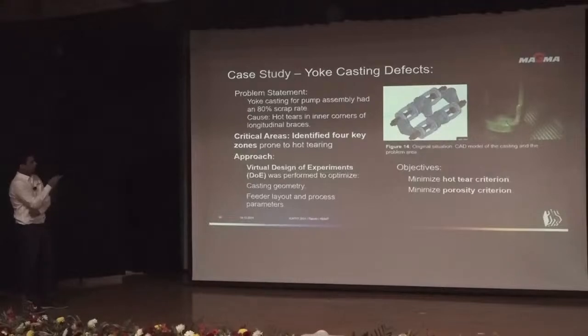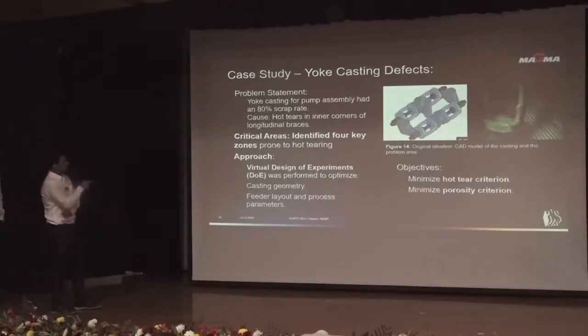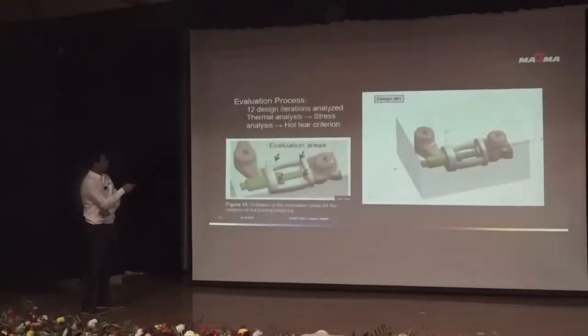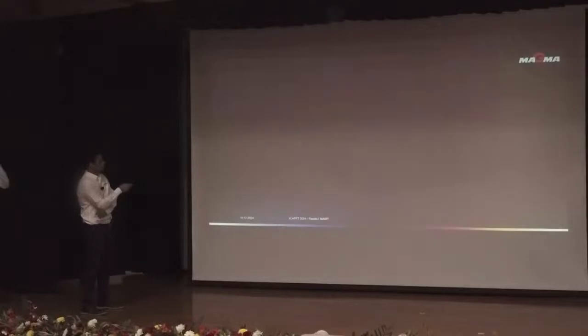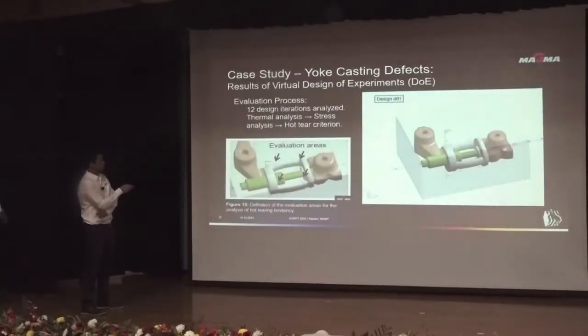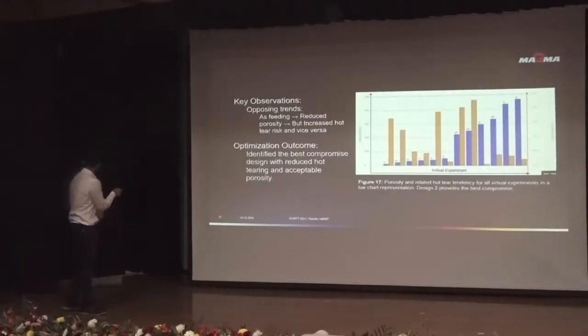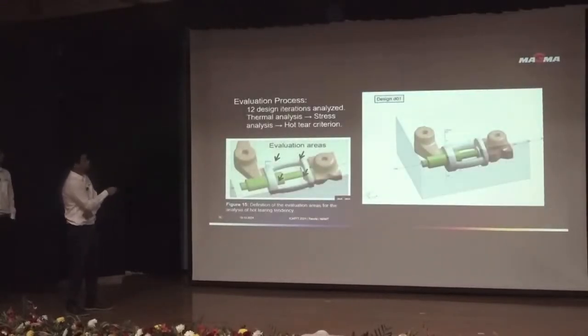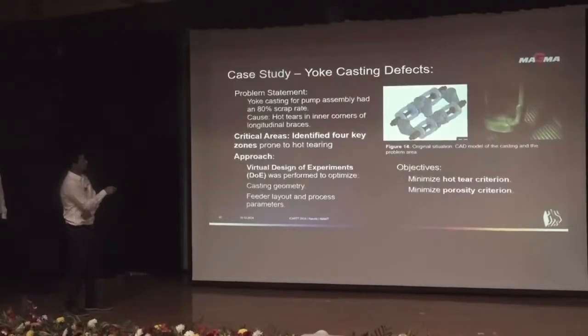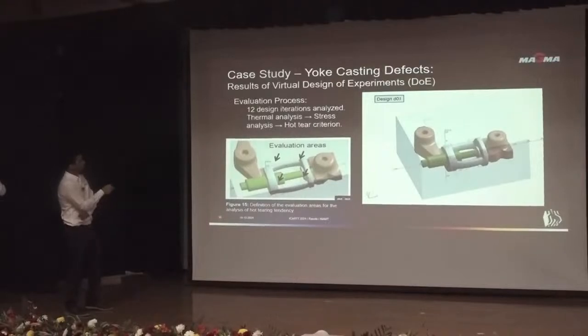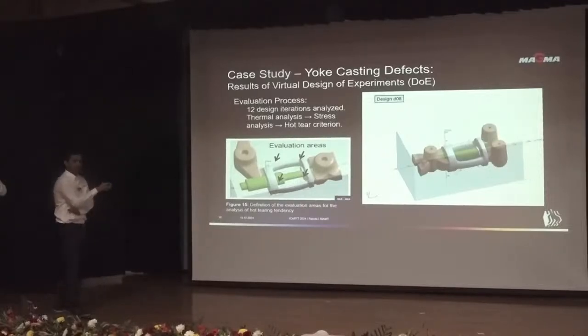So we identified those key zones in a casting. We did a virtual design of experiments, where we performed multiple designs in simulation to see which design would be the best for us. The objective was to minimize the hot tear criteria and also minimize porosity creation. So these are the 12 designs, where we tried to change the riser locations and the feeding efficiencies of the risers.